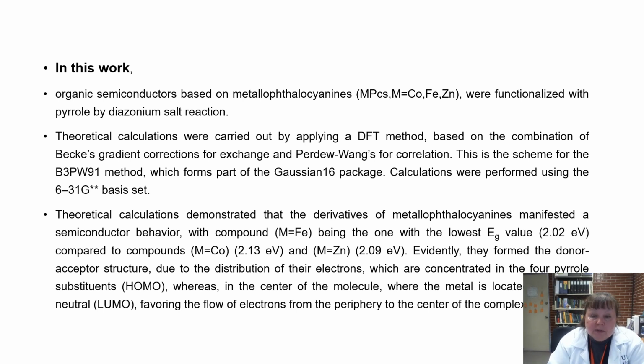Theoretical calculation demonstrated that the derivatives of metallophthalocyanines manifested a semiconductor behavior, with the compound with metal center iron being the one with the lowest Eg value, 2.02 electron volts, compared to compounds with metal center cobalt, 2.13 electron volts, and with metal center zinc, 2.09 electron volts. Evidently, they form the donor-acceptor structure due to the distribution of their electrons, which are concentrated in the four peripheral substituents, HOMO, whereas in the center of the molecule, where the metal is located, neutral LUMO, favoring the flow of electrons from the periphery to the center of the complex.